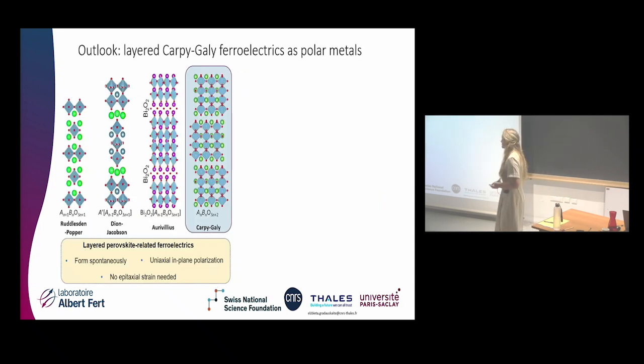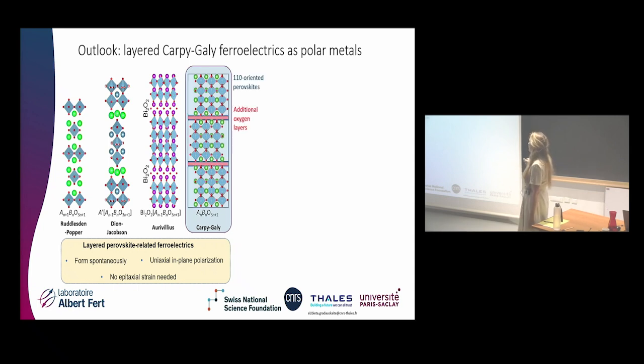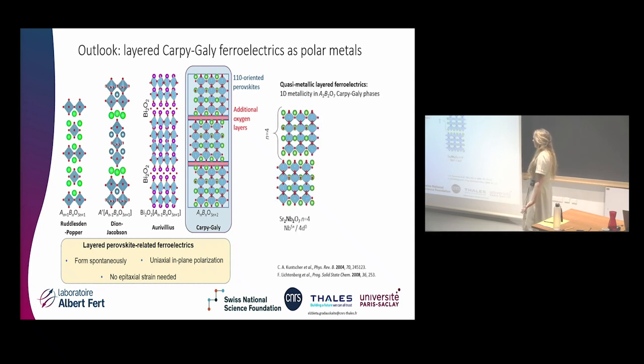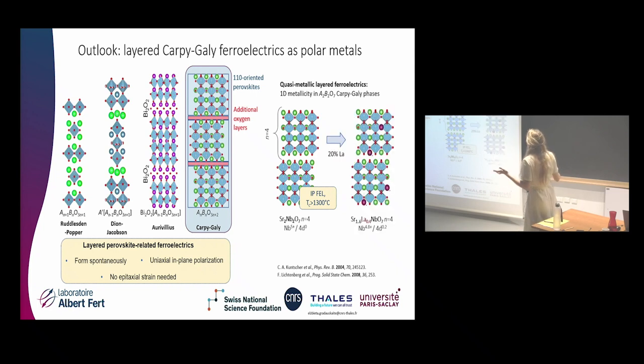And now just a quick outlook of what I started in my postdoc a few months ago. We're now working on the Carpy-Galy phases, seeing what they have to offer. And here we have 110-oriented perovskites interleaved with some additional oxygen layers. That's the general structure. And the reason why we're interested in them is that in bulk, it is known that these materials, like if we take n equals 4, the Sr2Nb2O7-type material, look a bit like this. We know that when it's not doped, it's a very nice insulating, ferroelectric material and has a very high TC. But the moment we start doping it with lanthanum, it turns into something that has metallicity along the a axis.